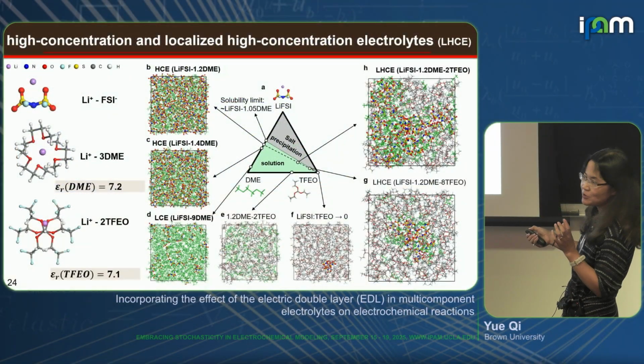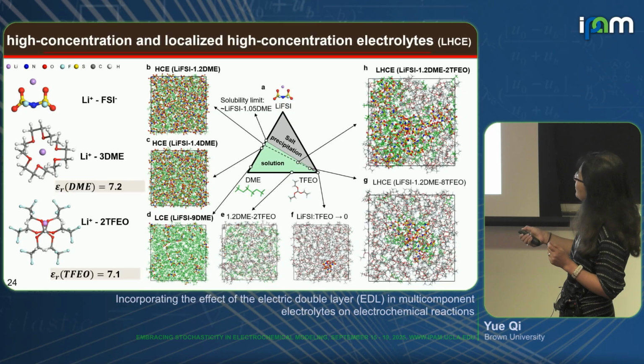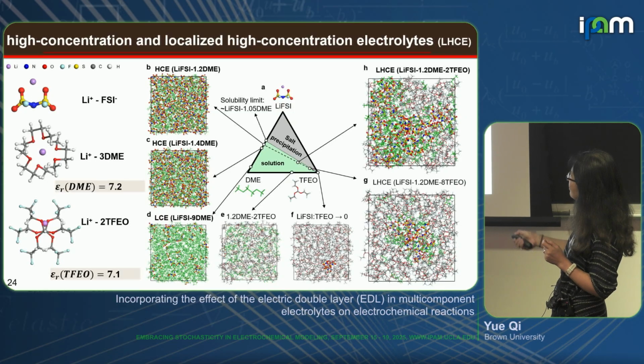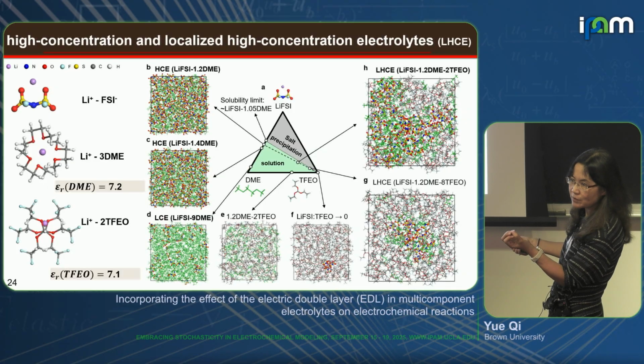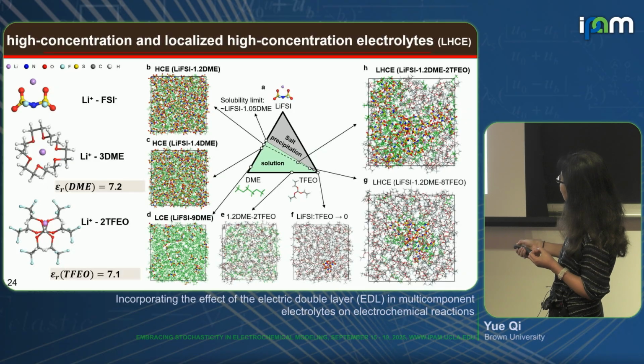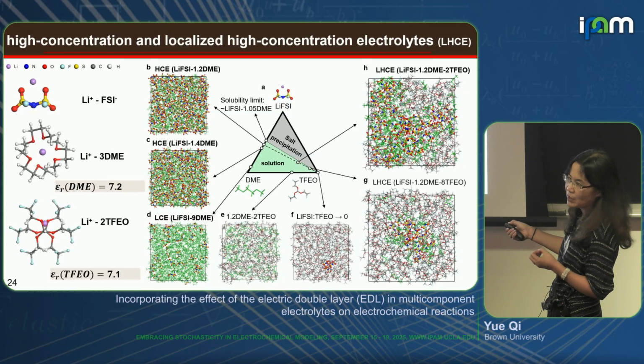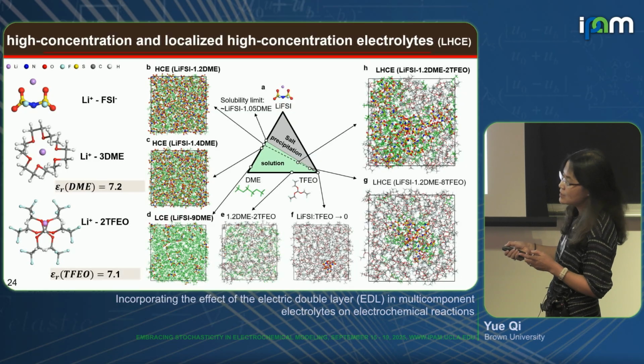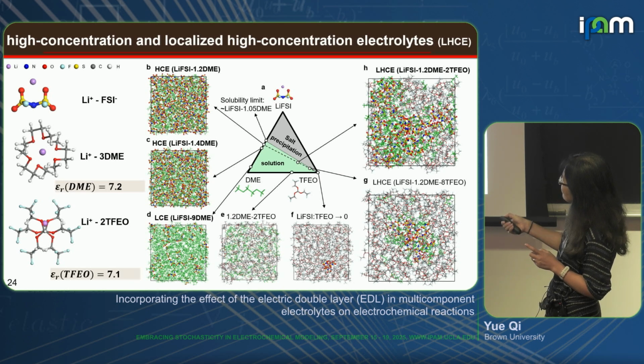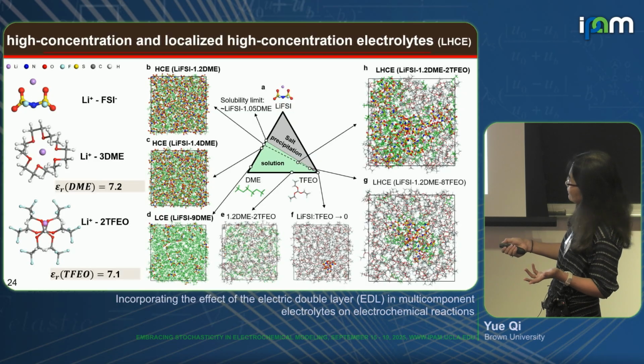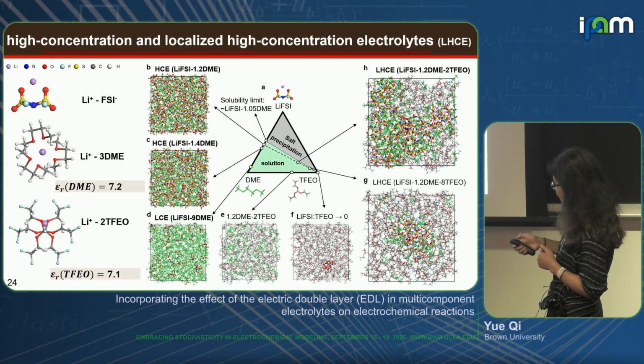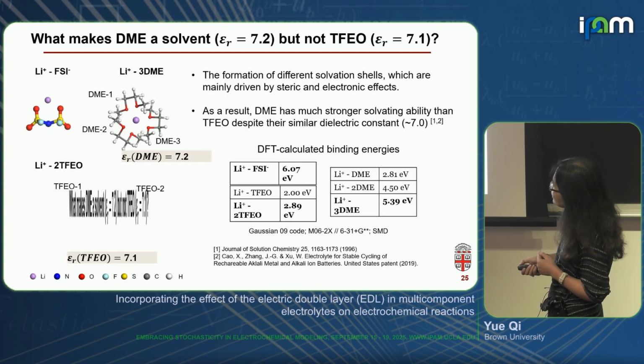This is actually quite interesting. This is a quiz problem. It has a very similar dielectric constant to the solvent, but it just does not dissolve the salt. You can see the salt in this TFEO is a cluster, right? All these are MD simulations. This is maybe 3 to 4 nanometers wide. And then these two, because they have similar dielectric constants, they mix completely, right? I have one question: why does this one dissolve the salt and this one does not? They have similar interactions with lithium, right? So it turns out, oops, what happened to this picture?